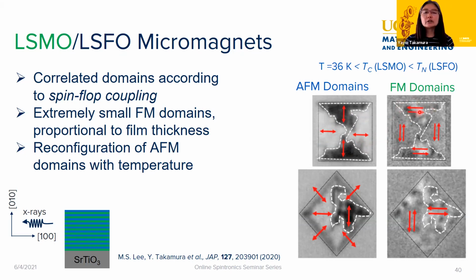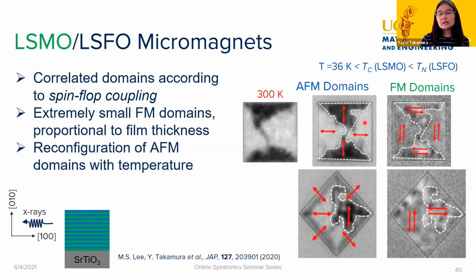We see in thin films as well that the domain size scales with the thickness of the film, so that's also what's going on here. But locally they're still maintaining this perpendicular orientation, so spin flop coupling is still taking place. What was also interesting is that if I looked at exactly the same micromagnet at room temperature versus these cryogenic temperatures, we can see that the antiferromagnetic domains are actually changing the position of their domain walls with temperature.